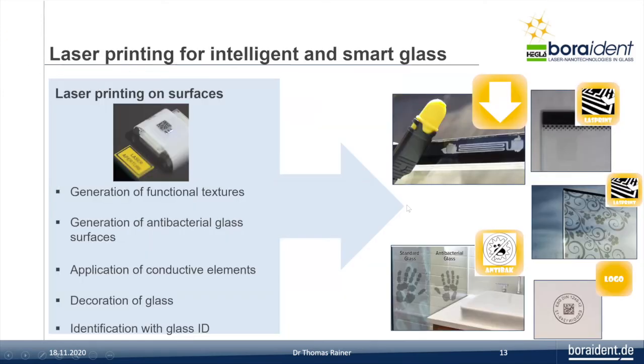So all these examples I showed you remove or modify the coating on the glass surface itself. The next examples bring material to uncoated glasses. It is possible to print with the laser material onto the glass surface itself. The technology is like an old typewriting machine. You use material coated with a special coating and transfer the coating to the glass surface itself with the laser acting as the hammer in this old typewriting machine.